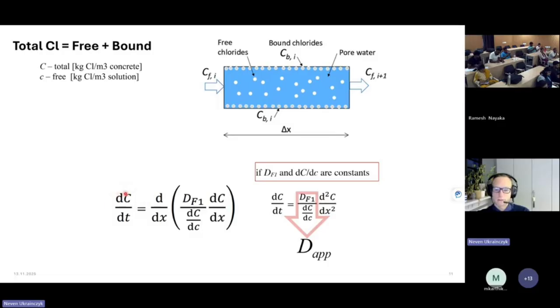Or if you have accumulation, so if what goes in is higher than what goes out, you have accumulation in the pore solution, and this is exactly the change of the concentration in time. So accumulation is equal to the input flux minus output flux plus the generation. We don't have the reactions here yet, but actually they are in the diffusion coefficient, which is actually in the accumulation. You can also model it as accumulation. That's why the reaction rate can come into the diffusion, because then it becomes part of the accumulation. So it's accumulating, but now not in the pore solution, in the total concrete, because we are having the total chloride concentration.